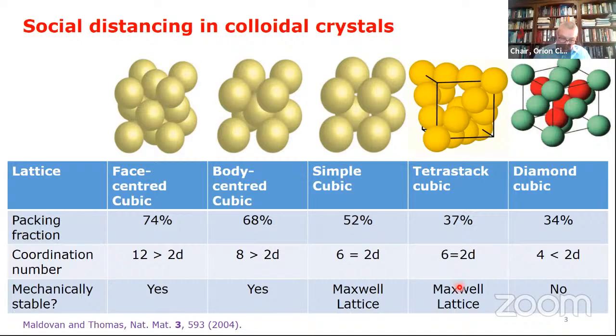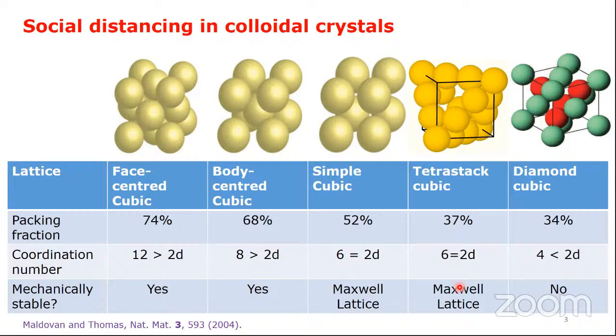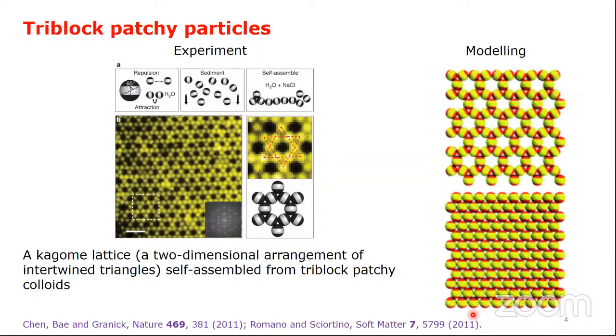The so-called Maxwellian lattices are in balance building blocks. The target structure is not only thermodynamically favored, but also kinetically accessible. The Granick group provided a major breakthrough in self-assembling colloidal open crystals about 10 years back. A Kagome lattice was self-assembled from tri-block patchy particles in a quasi-two-dimensional system. Here, the designer colloidal building blocks have equal size attractive patches at the poles across a charged middle band. Upon screening the electrostatic repulsion between the particles by throwing salt into the medium, the self-assembly was observed. This seminal work provided